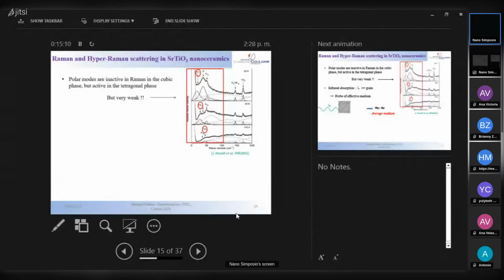So if you look at the Raman spectra, the polar modes are inactive in Raman in the cubic phase, as I told you. But remember, in this titanate, you have a transition from cubic to tetragonal at one moment. So the modes are active in Raman in the tetragonal phase. But if you look at the Raman spectra here, this mode which we are looking at is this bump here. It is very, very weak, and it is embedded into a very strong background signal. So that's not very useful. I mean, Raman is not a useful technique to measure this mode.